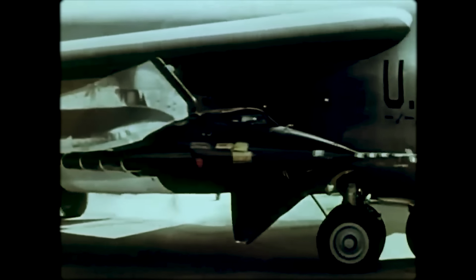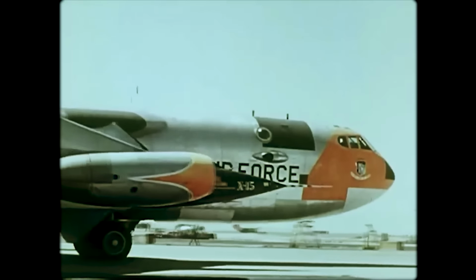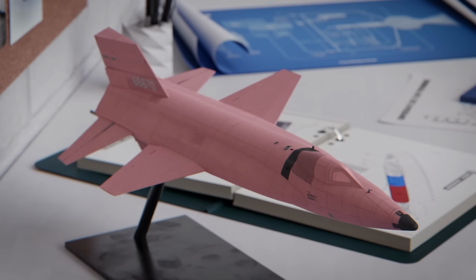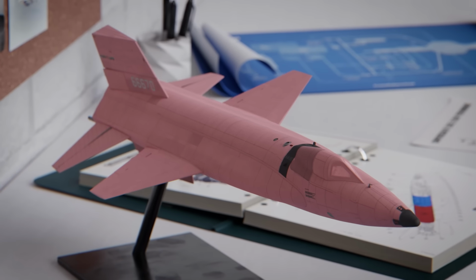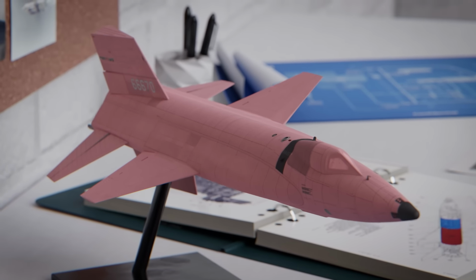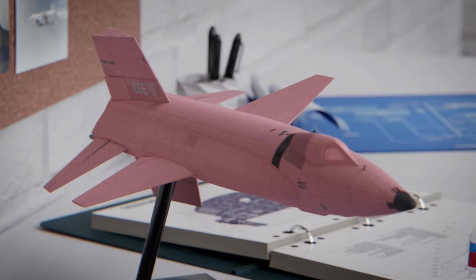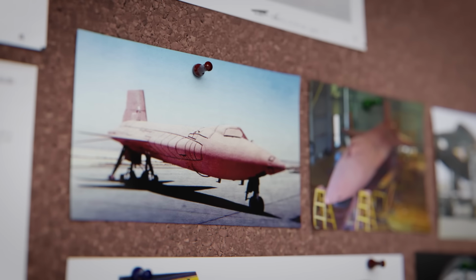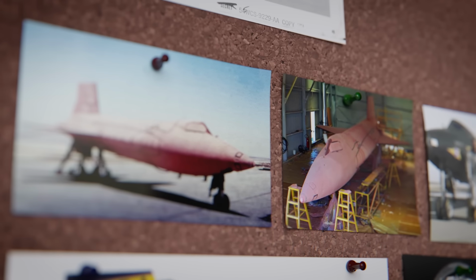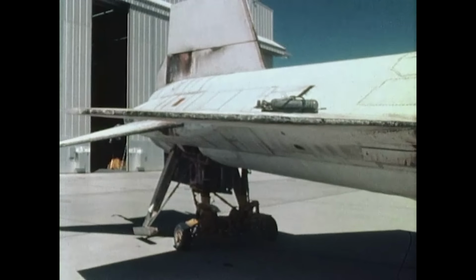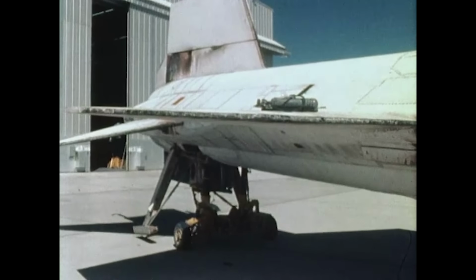To make matters worse, one of the principal lessons learned during the X-15 program was that the hot pink foam ablative coating sprayed onto the plane for the top speed flights was completely unusable for the Space Shuttle. An ablative coating is a sacrificial material designed to gradually burn and fall away from the aircraft, pulling the heat with it. However, the ablative coating of the X-15 had a nasty habit of burning away from the nose of the plane and attaching itself to the cockpit windows, rendering the pilots completely blind, which presented a bit of a problem.